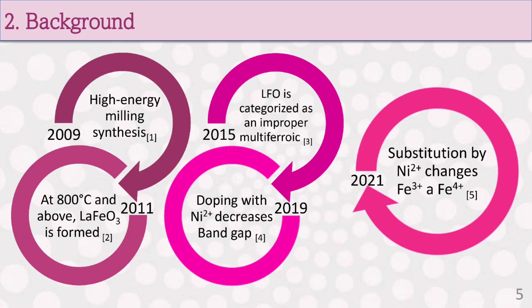Background. Over time, work has been done on the synthesis of lanthanum ferrite, first to obtain successful synthesis to be able to study its magnetoelectric properties. In 2009 it was successfully synthesized by high-energy mechanical milling. Later in 2011 it was discovered that at 800 degrees Celsius ferrite is obtained without secondary phases. Then in 2015 it was categorized as a multiferroic of improper type, which made interesting the need to modulate its properties by doping, one of them in 2019 with nickel, which proved to decrease the band gap of the material.